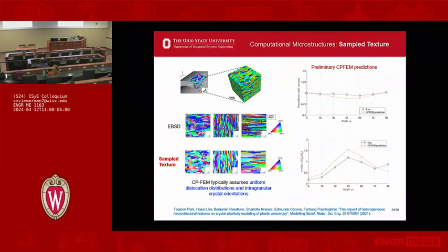Even in that, we realize that, for example, here the trend is not correct. That even told us something in this model is not enough. That needs to be done. And we realized that they only measured these things afterward. This is a tube that was extruded. They just said this is what it looks like. But the tube itself went through a process to get to that point. That created certain deformation in it, residual stresses that we did not account for.